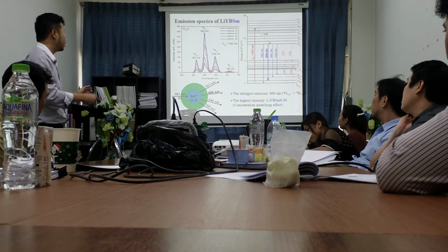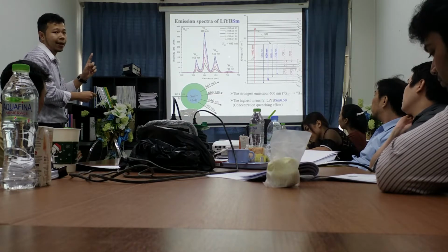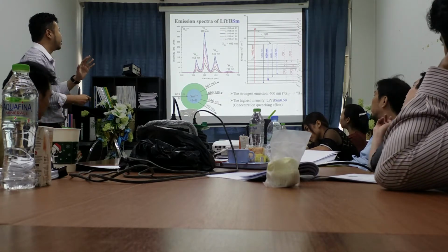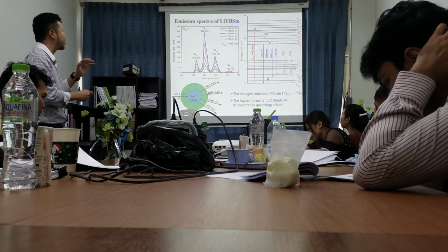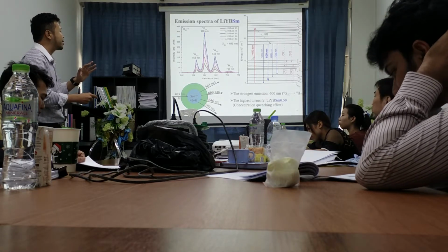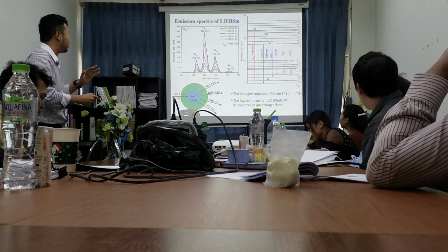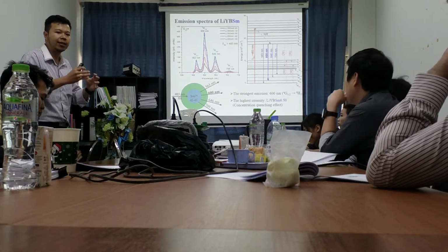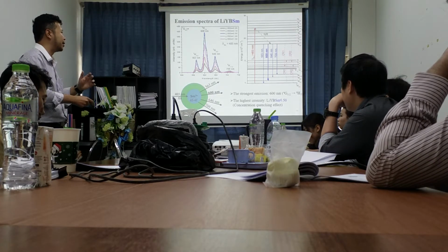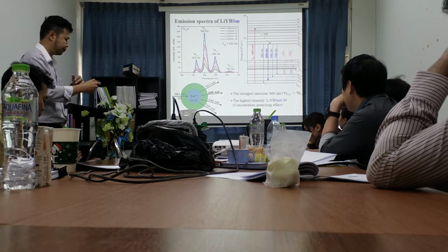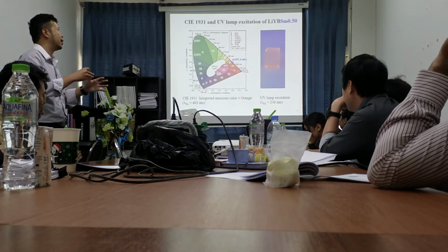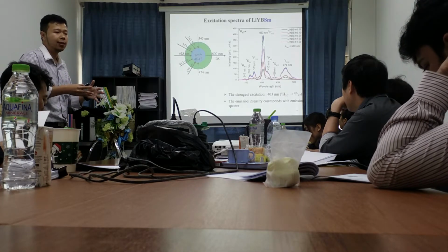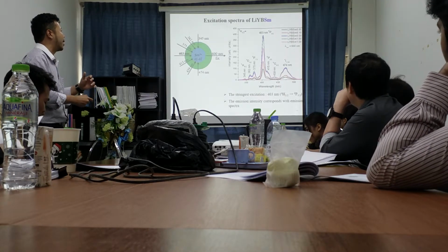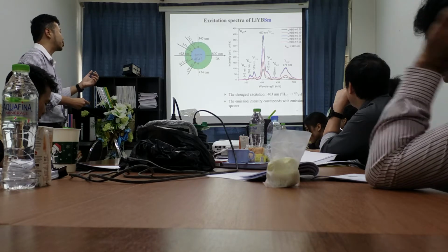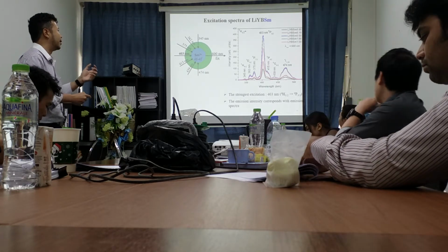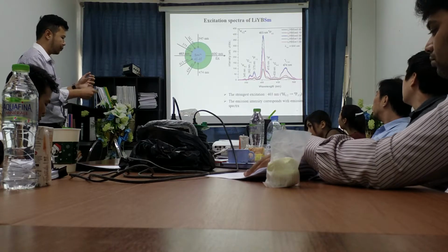nanometers. I took the most absorbed band to excite the glass for the emission spectrum. It performs the strongest emission at 600 nanometers from the luminescence level 4G5/2. And we found the concentration quenching effect, which showed the highest intensity for the 0.5% Sm glass. Next, to confirm the excitation wavelength, I measured the excitation spectra and it corresponds with the emission spectra, showing the strongest excitation at 403 nanometers.